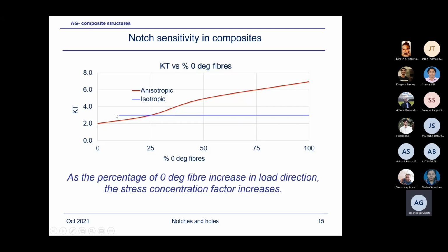But as the anisotropy increases, as you can see, the KT can reach almost 7. What we mean by anisotropy is the percentage of 0-degree fibers along the load direction keeps on increasing for a layup. So if you have a unidirectional layup, say, 100% zeros, that is a tape laminate, and if you drill a hole in it and try to load it, you will find the anisotropy. Due to this, the stress concentration factor is almost 7.